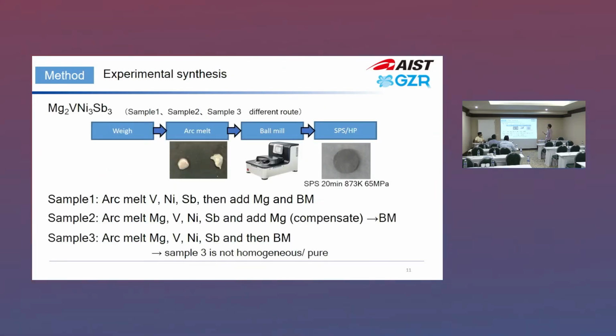So experimental synthesis is pretty straightforward. Just weigh the elements and arc melt all the samples together, or sometimes remove the magnesium and add it later, because magnesium just evaporates everywhere. Then mix and homogenize them together, and we use SPS or hot press at higher temperatures, like 600 C, 800 C, to get these pellets. So this is a polycrystalline sample.